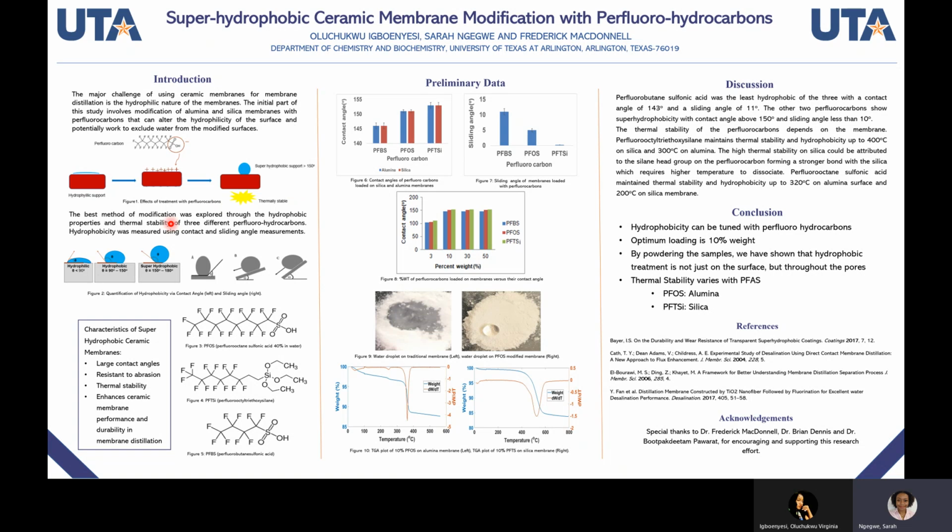The best method of modification was explored through the hydrophobic properties as well as the thermal stability of three different perfluorohydrocarbons, PFOS, PFTS, and PFBS. Hydrophobicity was measured using contact angle and sliding angle measurements. Contact angle is the angle made between a water droplet and the modified surface.